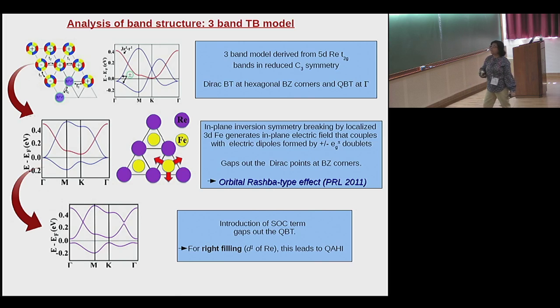And there is another very interesting effect. Since the irons are sitting here and the rheniums are sitting there, there are these two triangles, and the iron basically breaks the in-plane inversion symmetry of these rhenium atoms. That gives rise to an in-plane electric field by this symmetry breaking, which couples with the electric dipole that is formed by these two pairs of this non-Kramers doublet of the Eg pi. And that gives rise to an orbital Rashba type effect, which opens up a gap at this K point at the corners of this Brillouin zone. Now, if you include the spin-orbit coupling, with the right filling, that makes it an insulator, opening a gap also at the gamma point.